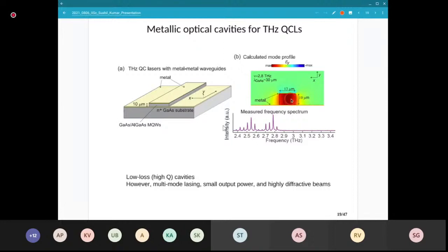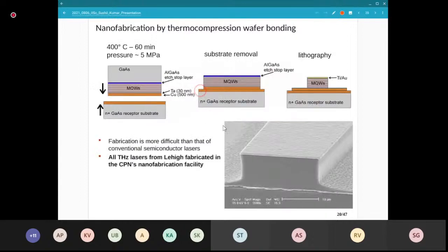This is a mode calculated through a finite element solver. The red color means the electric field, which is in the vertical direction. This is what we call a Fabry-Perot laser. For those who know Fabry-Perot cavities, it's just a rectangular cavity; you cleave it on both sides, you make facets, and they become reflecting facets. These are by themselves horrible lasers, not like typical lasers that we see from our laser pointer. Our laser pointer might also have something like this, a VCSEL or a Fabry-Perot laser, and it has a fairly nice beam. But if you were to make this terahertz laser, it will have a horrible beam. I'll show you the beam in a bit.